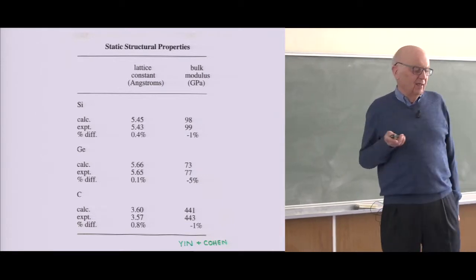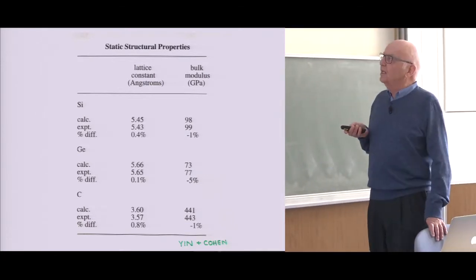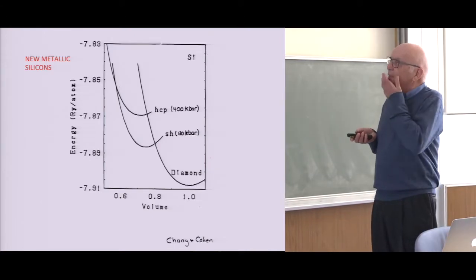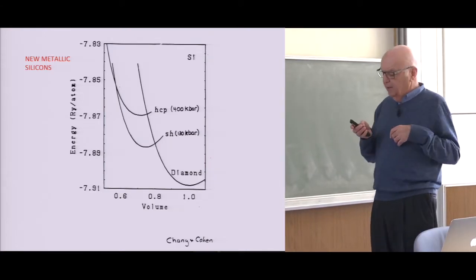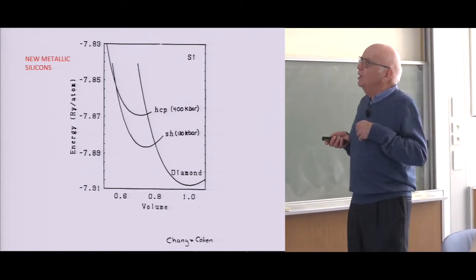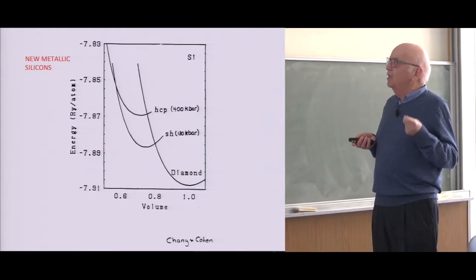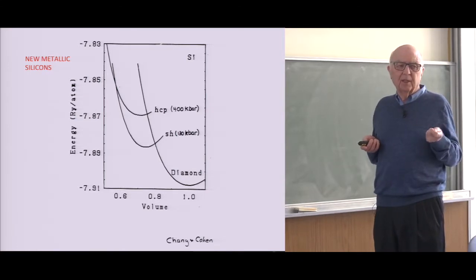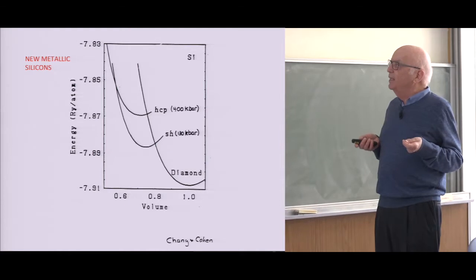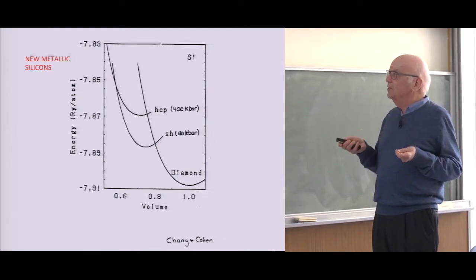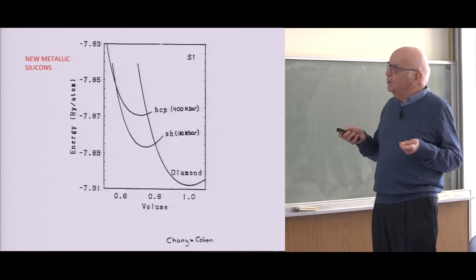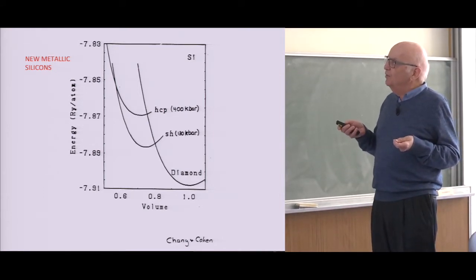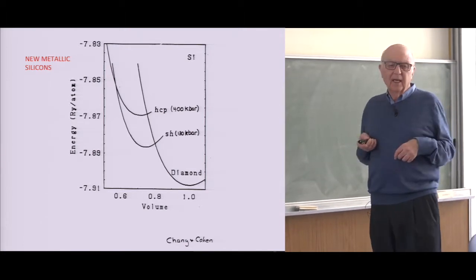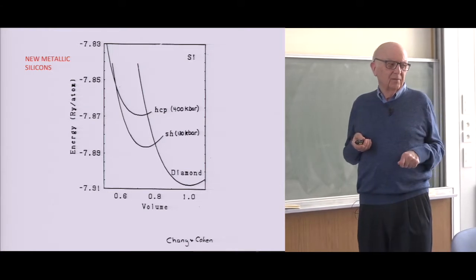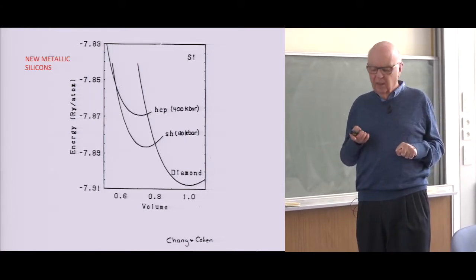Anyway, calculations have been done, many on the same elements, but hundreds of materials have been looked at. Now, this is an interesting one because I want to come back to it later. Here are two special structures of silicon that you get at high pressure, theoretically. Here's a total energy as a function of the volume. The first one is diamond, the usual one, it's a semiconductor. We found that you could get a simple hexagonal one and a hexagonal close-packed one. And you could predict everything about them, including the fact that they're metals and superconductors.